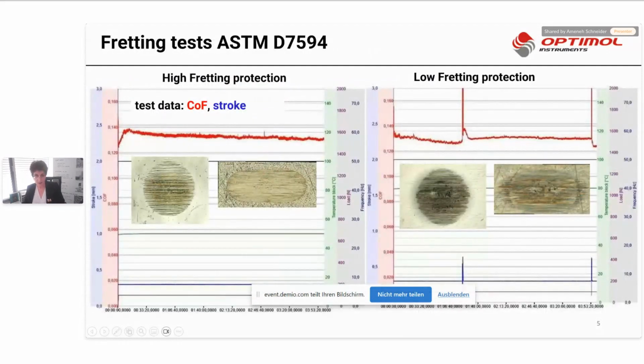Here, this slide is a very, very simple example for this fretting that you can see how it works. Adjusting this parameter, running the test, you can see here immediately on your monitor from the SRV machine that the coefficient of friction value is very nicely stable during all 4 hours. The time is 4 hours and 13 seconds for the running in.